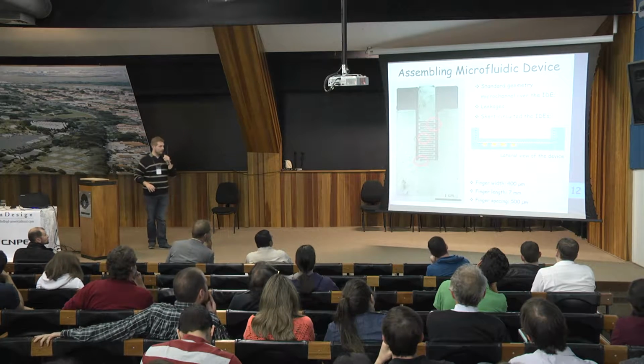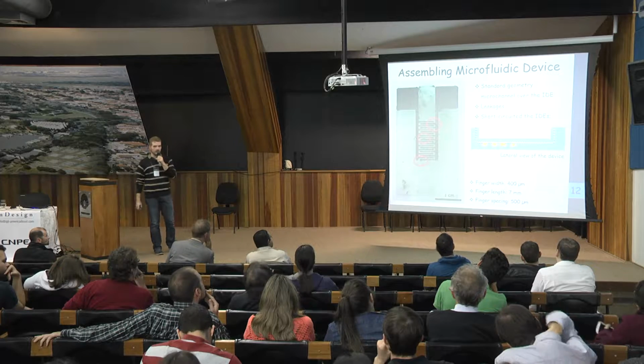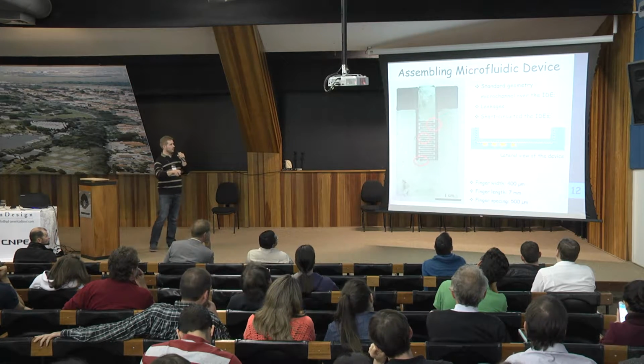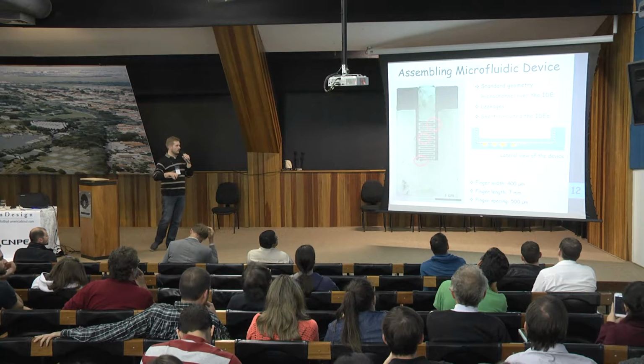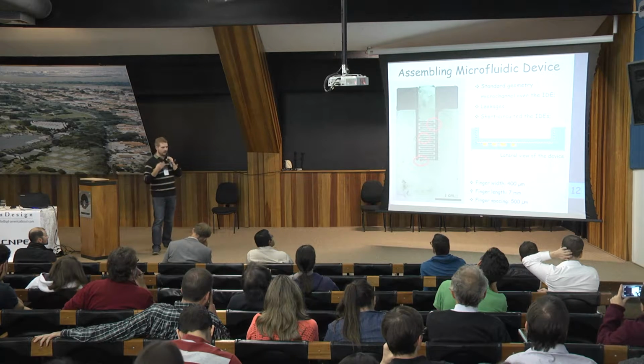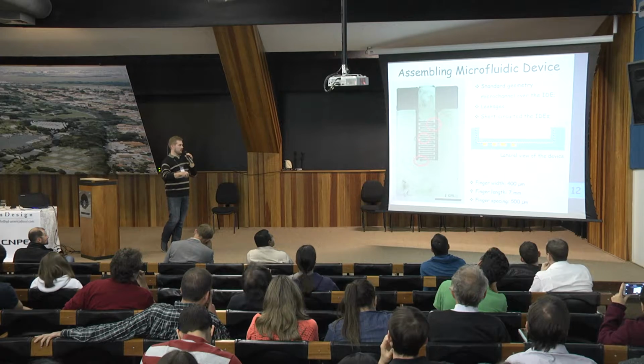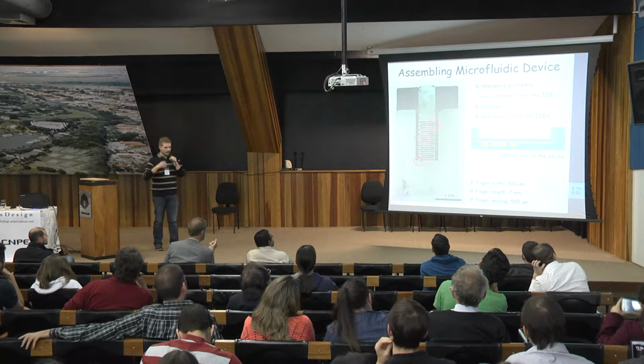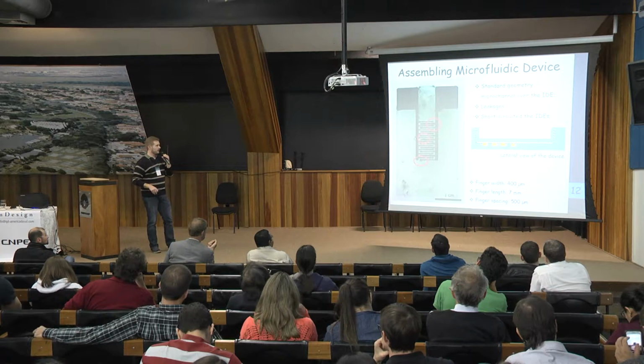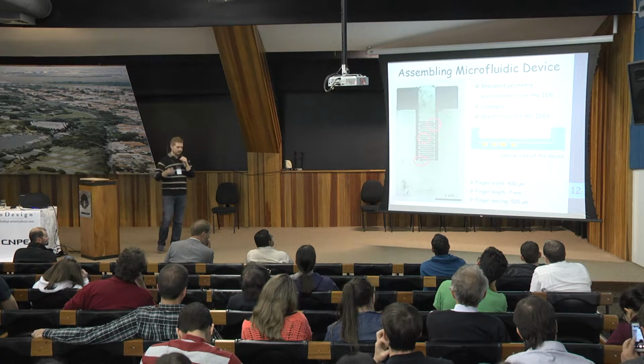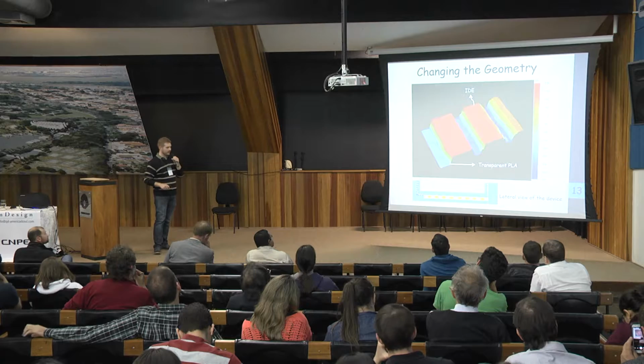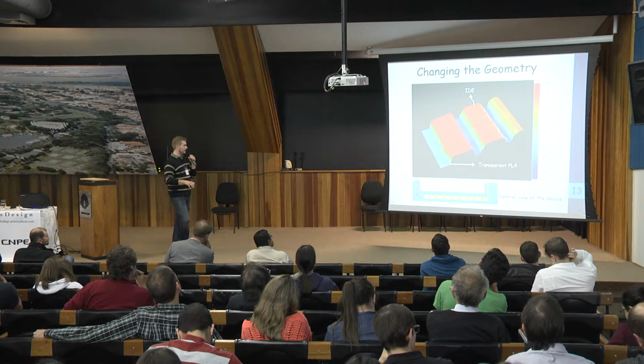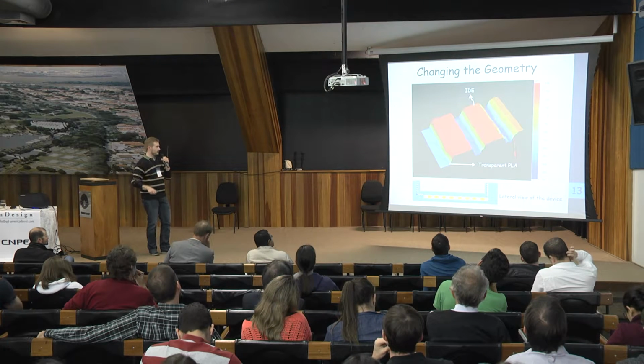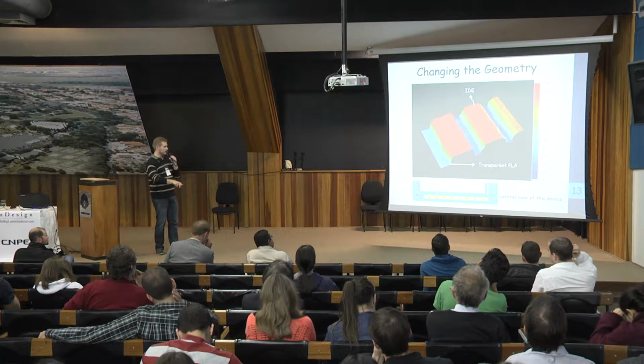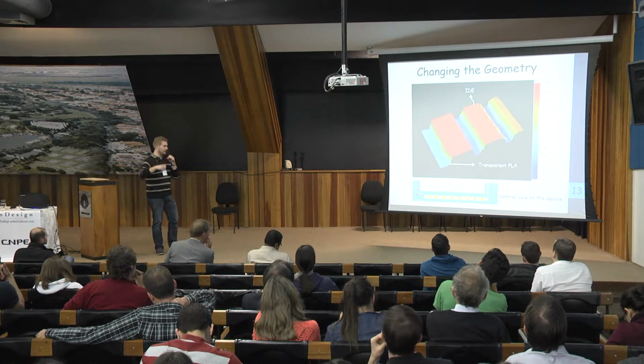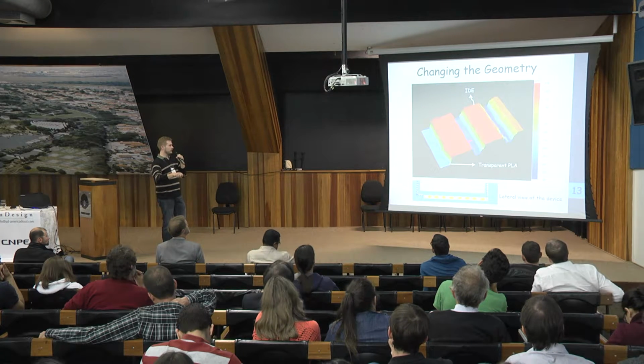The next step was then to try to make a microfluidic device. We started with a standard geometry with the channel above the interdigitated electrodes. However, this kind of geometry couldn't be applied because there are always leakages, and when you try to seal it this way, you short-circuit the IDEs. And one of the great advantages of this technique is that you can change the geometry almost as you want. So we tried a new approach. We 3D printed the electrode as the wall of the channel, and the fluid will pass among the fingers, and we measured the response between them.